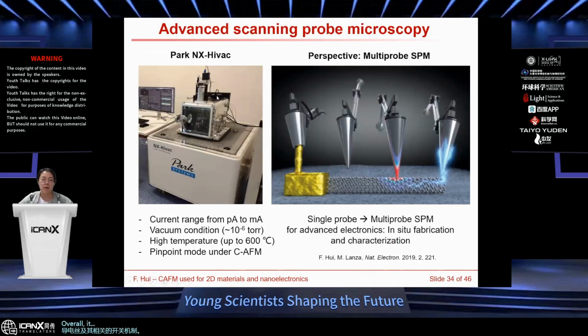Overall, it is very meaningful to develop advanced SPM, scanning probe microscopes. Here I show one example of an AFM that I used 2 years ago. This is the vacuum chamber, and this AFM allows us to connect with an SPA, get a large current range, and conduct the experiment under high vacuum conditions. It can also allow us to measure the samples at high temperature.